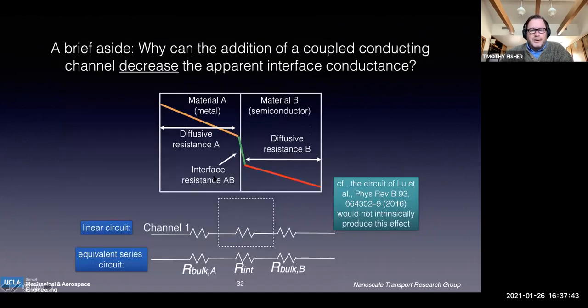So here's a little tutorial. One of the things that people ask me is, when I add a channel of conductance, how can it decrease the interface conductance? And really what it comes down to is, when you're adding different channels of energy flow and using a linear theory to interpret the interface conductance, if you have parallel resistors on both sides of the interface, you can actually add a channel but still get less apparent conductance. It's just an apparent conductance, because an interface conductance model doesn't really account for the slopes of these lines in the bulk material.